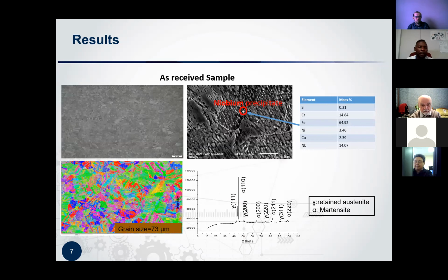And then we did the characterization from the sample we received from that company. As you can see, as expected, because 17-4 is a martensitic stainless steel, the matrix is martensite. And with the help of EDS, we also found that there are niobium precipitates forming. The reason being that since this is a stainless steel, and with stainless steel you need chrome, this niobium is added as a sacrificial element to prevent the formation of chromium carbides, because if they form, they reduce the corrosion resistance. So you are bound to have this niobium precipitate, and they also help in terms of increasing the strength.